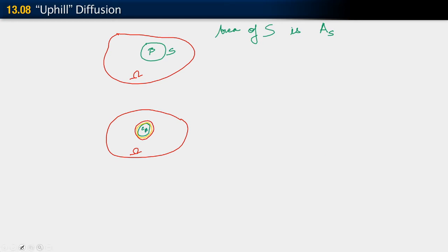Outside of it, well outside of it, it is C alpha. As we go across that interface of some thickness, the concentration is changing. That's where we pick up a concentration gradient. So this has replaced the area with some region of finite width.